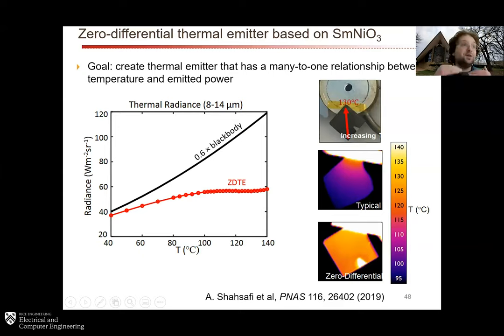And so essentially, if the emissivity is decreasing as the temperature is increasing, what that means is not that the heat is leaking out at other wavelengths, it's that the heat stage and the temperature controller are essentially pumping less heat into it to keep it at a certain temperature. So there aren't any thermodynamic issues with it, but also you don't have an increase in emissivity at another wavelength to compensate.